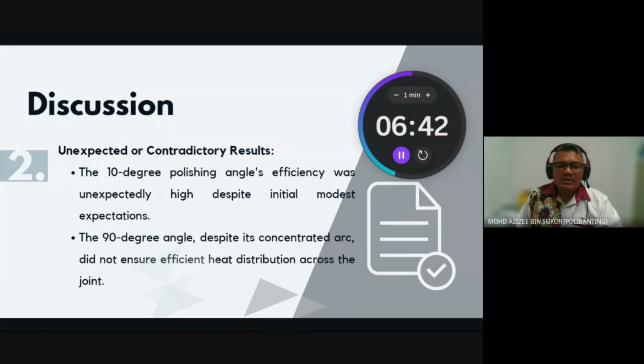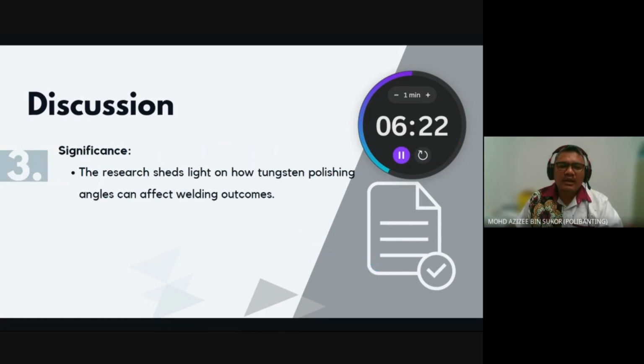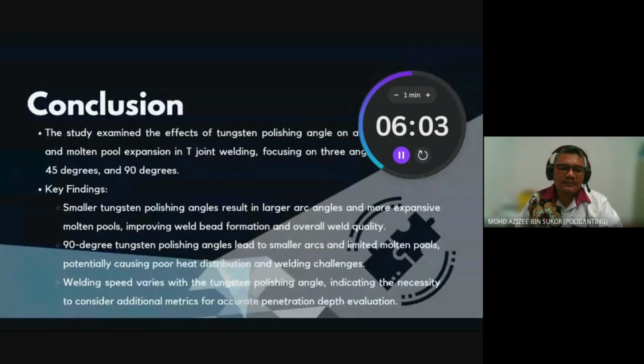The unexpected result: the 10-degree polishing angle's efficiency was unexpectedly high despite initial modest expectation. The 90-degree angle, despite its concentrated arc, did not ensure efficient heat distribution across the joint. The ideal tungsten polishing angle varies with the welding task. While smaller angles favor wider welds, larger ones benefit thicker welds. Excessively large angles risk poor heat distribution. This study deepens knowledge on tungsten angles in T-joint welding, guiding optimized processes.